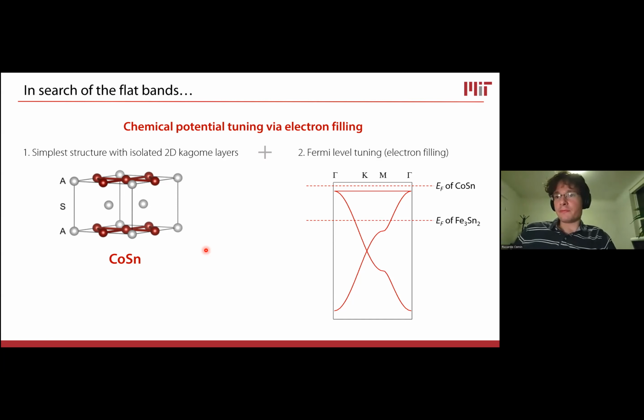And the reason for doing that is because there is a lot of interest in using the flat bands as a starting point to achieve some correlation phenomena, of the same kind as the ones that can be achieved in magic angle twisted bilayer graphene, where the flat bands are created by the Moiré engineer. So one approach to this that we followed together with Joe, was to try and look at a simpler system with more isolated Kagome layers and with cobalt instead of iron, because cobalt has extra electrons.